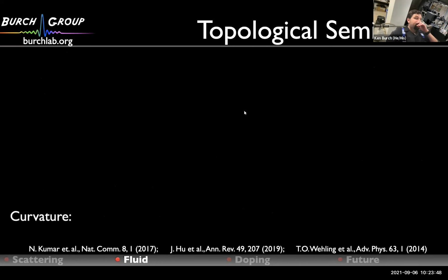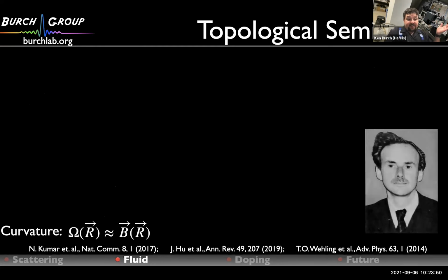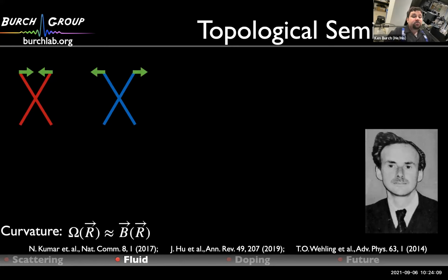Okay, so with that in mind, are there materials that have interesting band structures related to this Berry curvature? And the answer is yes, otherwise I wouldn't be bringing this up, right? So it goes in some sense back to Dirac. If you take a Dirac semimetal, so you have this linear dispersion in 3 dimensions, and you either break inversion or time reversal, you'll find that you split your Dirac node in two, right? Into two copies, where the spin is either collinear or anti-parallel to the momentum.